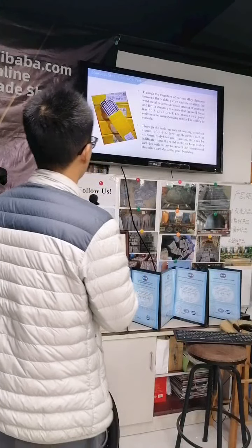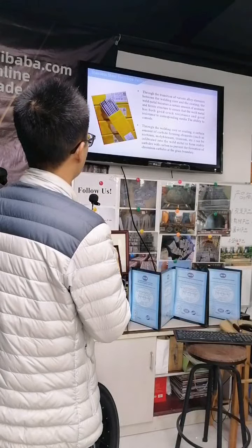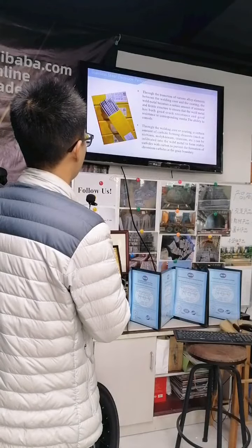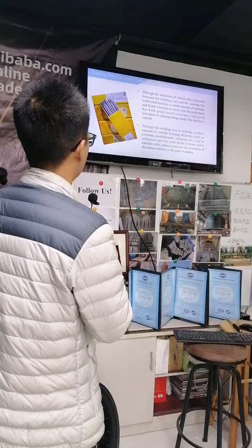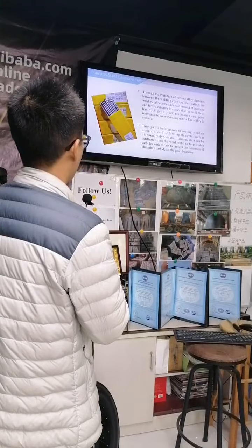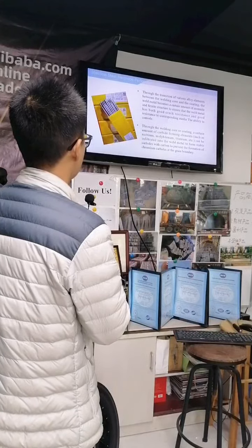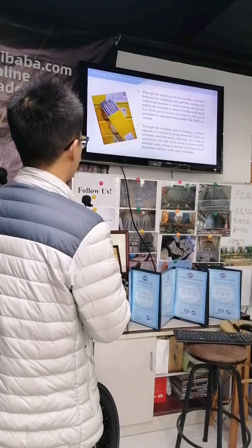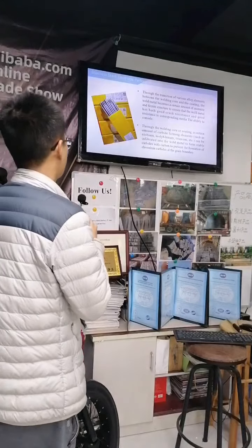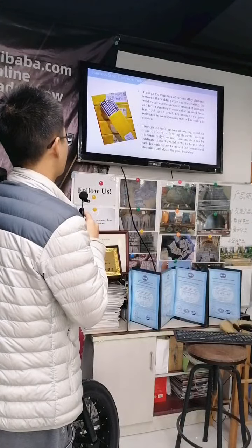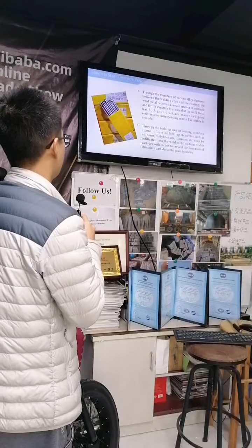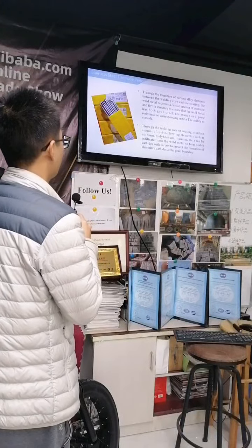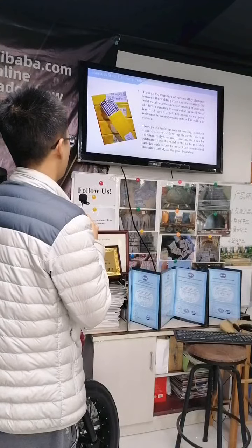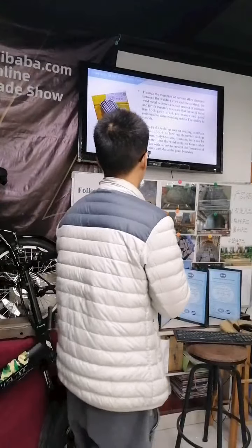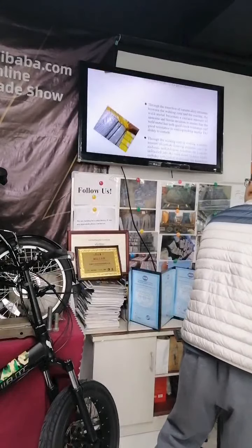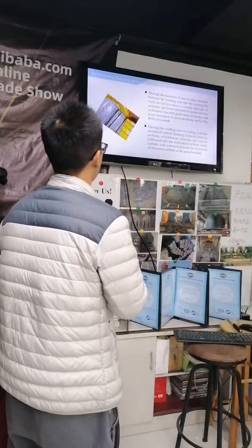Through the transition of various alloy elements between the welding core and coating, the weld metal becomes a certain amount of austenite and ferrite structure, to ensure that the weld metal has both good crack resistance and good resistance to the corresponding medium. Through the welding core or coating, a certain amount of carbide forming elements, such as niobium, molybdenum, titanium, etc., can be infiltrated into the weld metal to form stable carbides with carbon, to prevent the formation of chromium carbides at the grain boundary.